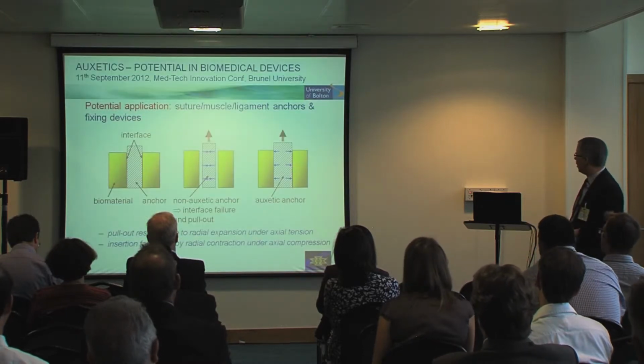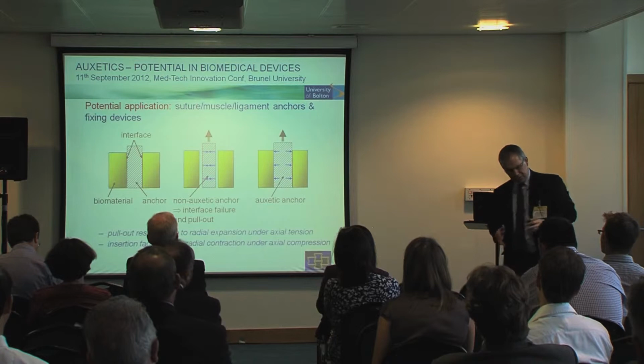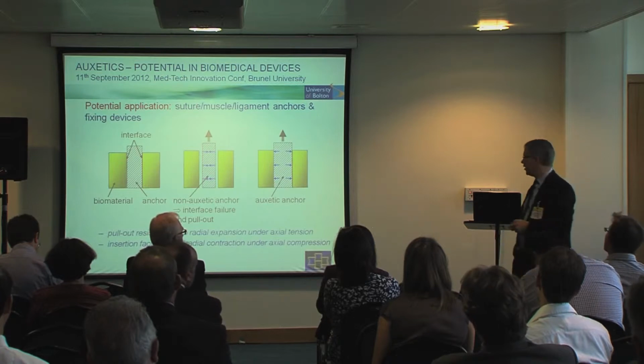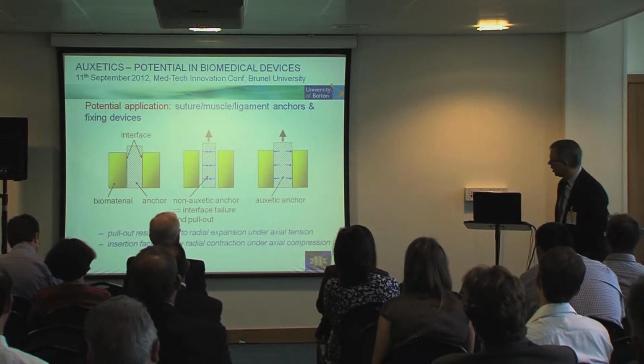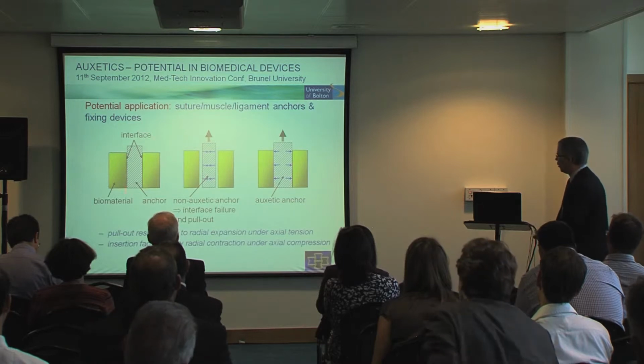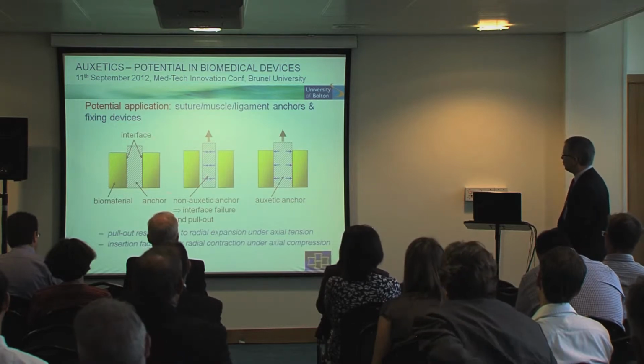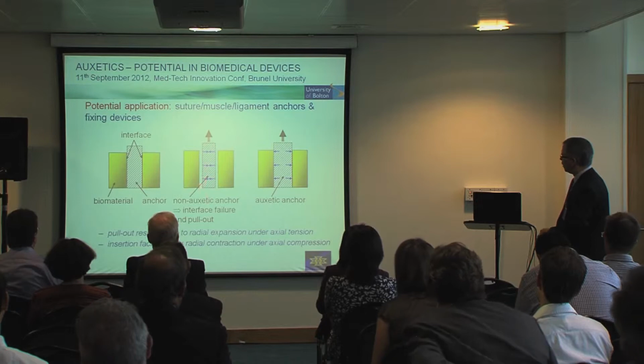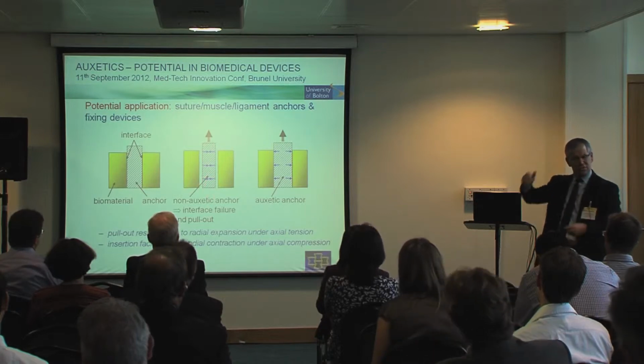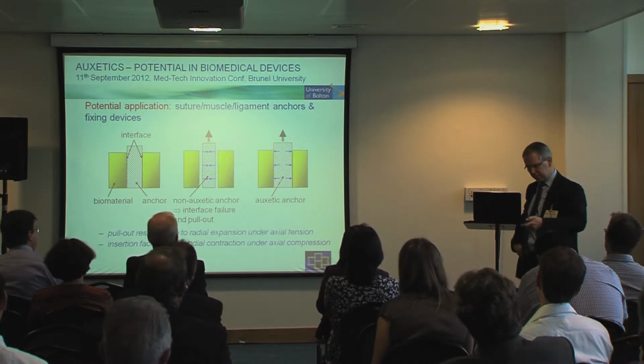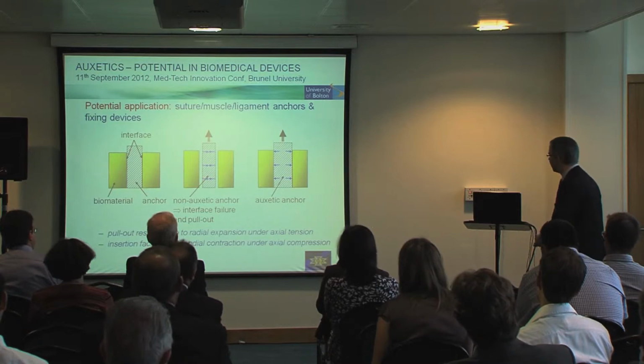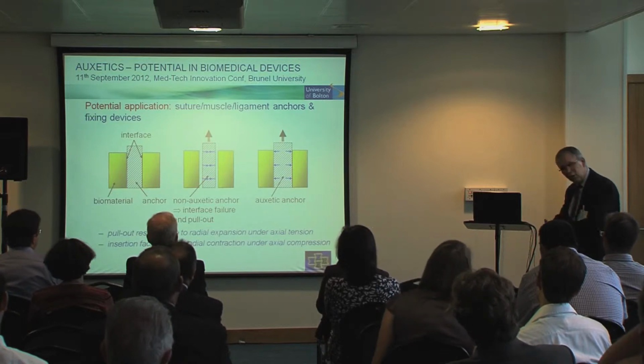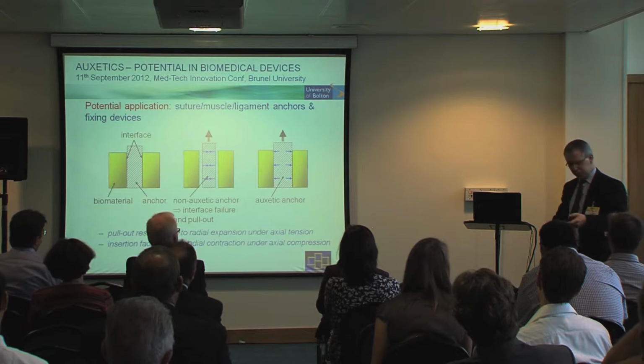We can look at the ability of the auxetic to anchor into a surrounding material in some way. So this is an example. You've got an anchor surrounded by a biomaterial in this case. If it's a normal anchor material, then if it's under tension, it will contract and you'll get failure at the interface. If it's an auxetic anchor, it will expand and lock into the material, so you should get improved anchorability.